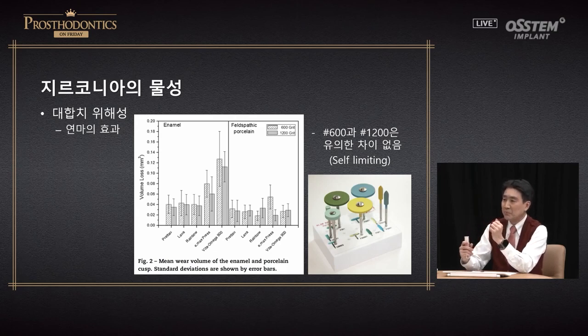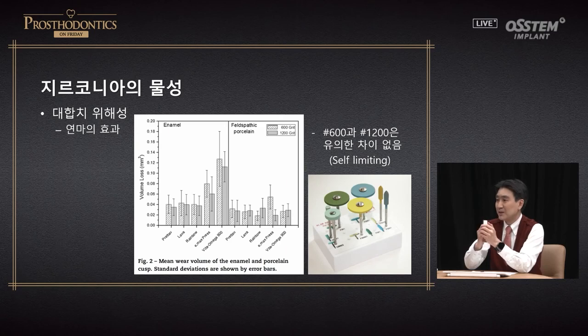There was something interesting here, the effect of polishing. As you have mentioned, you need to do polishing to prevent wear on antagonist. I checked the level of impact of polishing on antagonist wear. I looked at the study, but there was no impact. I did study it in engineering. This is already a known concept, the self-limiting concept.